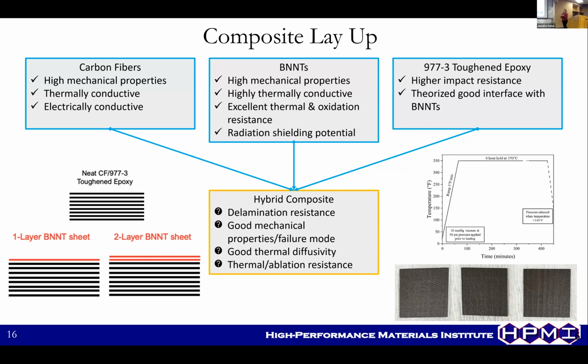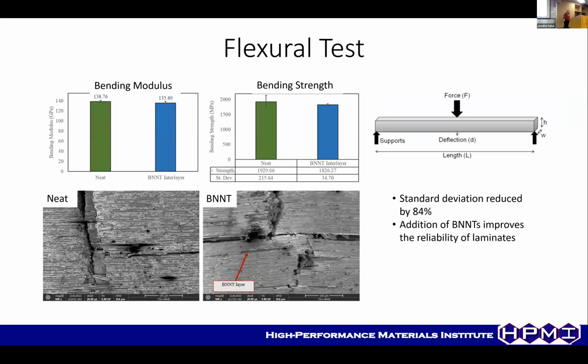So in this study, this carbon fiber 977-3 prepreg has an 8-ply stacking sequence. In one of them, we put 1 layer BNNT sheet, and then in the next one we put 2 layers of BNNT sheet at the surface. You can kind of see where we're going with this. We did some flexural testing of these composites.